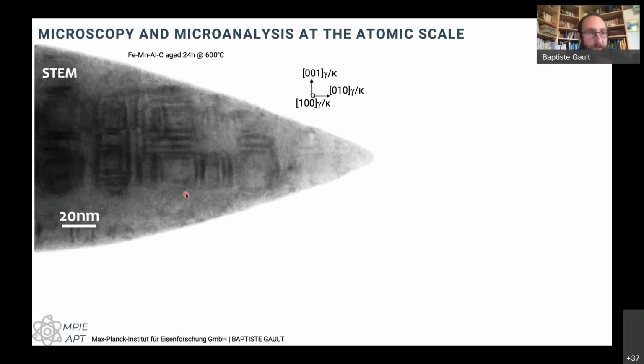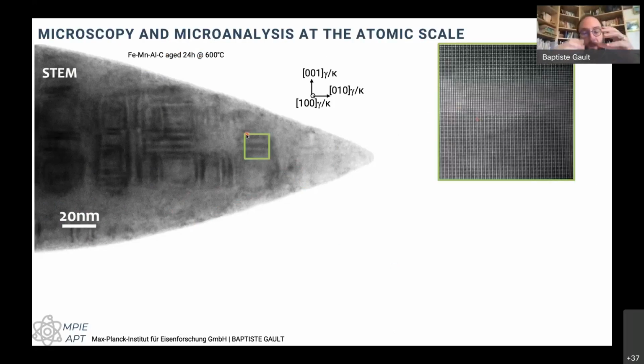And what we've been trying to really push at the Institute over the past, whatever, decades, or even before I started, was the ability to combine the structural information we can get from a transmission electron microscope. So here we have a precipitation strengthened austenitic steel, and you can see there's a matrix and there are precipitates, and the atoms inside the precipitate and the matrix are not arranged exactly in the same way. The precipitates are ordered with long-range ordering, where we have certain atoms occupying a certain site of the lattice and other atoms occupying another site. But looking at these types of specimens through the lens of the TEM, we get a projection through the entire specimen. So we have just an idea of how the sample looks when we look through this, not exactly where each atom is located.